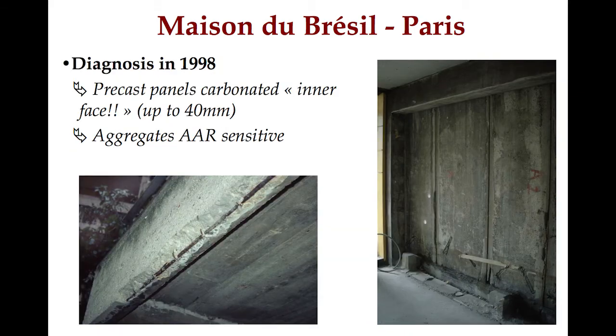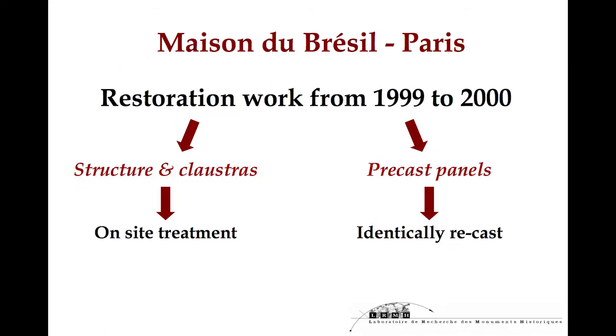The diagnosis showed that the precast panel was carbonated on the inner face up to 40 millimeters, and the aggregates were AAR sensitive. So, concerning the restoration work, this restoration work was performed from 1999 to 2000. For the structure and claustra, there was on-site treatment, and for the precast panels, they were identically recast.